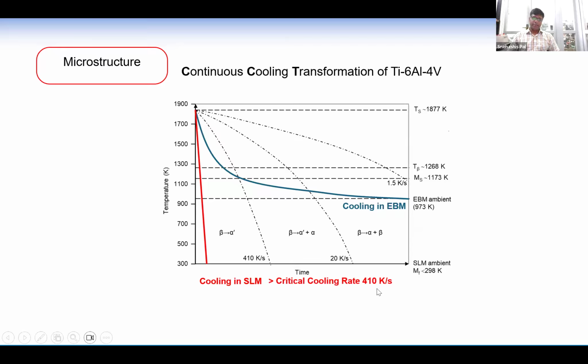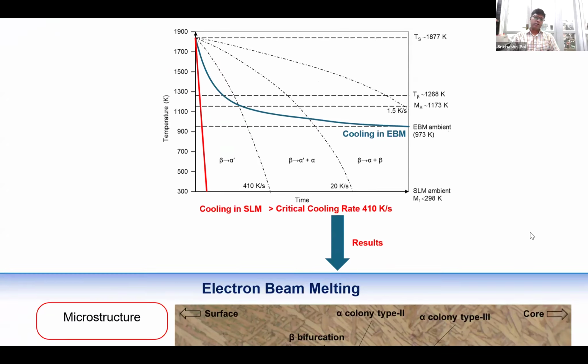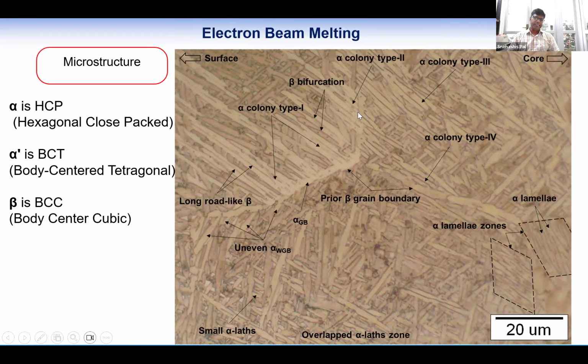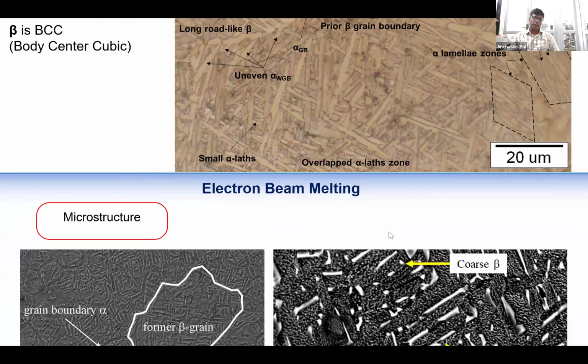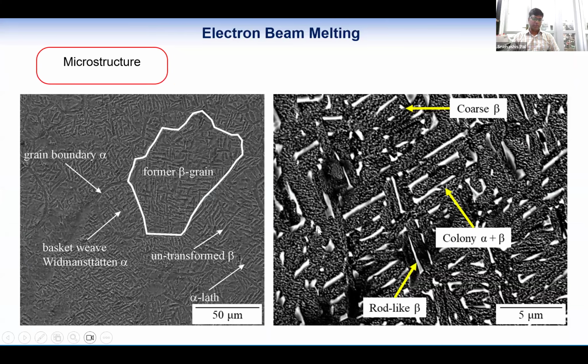The critical cooling rate, for titanium, is 410 degrees centigrade per second. If it is higher than that, then a different microstructure will be created, right? Accordingly, the microstructure for electron beam melting is quite similar to the casting process. This is an example for the titanium alloy, titanium 64. There are a lot of other possibilities, but still, with electron beam melting there is less possibility to tailor the microstructure.